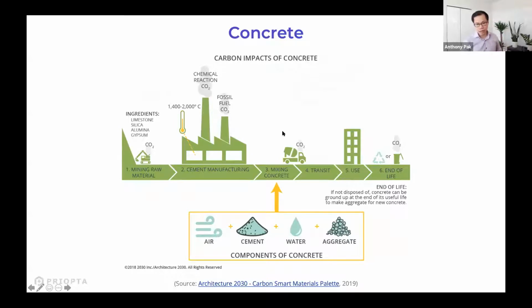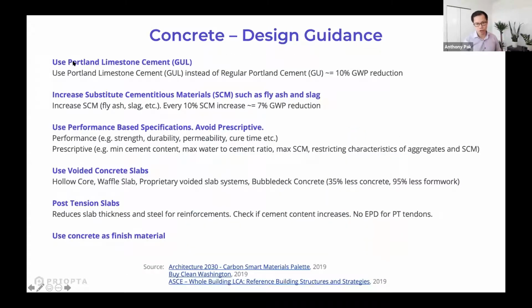So what are some of those strategies? You can use Portland limestone cement, also known as GUL or general use limestone. This is in contrast to regular Portland cement. The difference is that you're basically adding a bit more limestone into your concrete mix and reducing the cement content. That's low-hanging fruit. I don't know if this is standard practice in Nashville, but definitely ask your suppliers for this. That can lead to about a 10% reduction just on the concrete mix level.